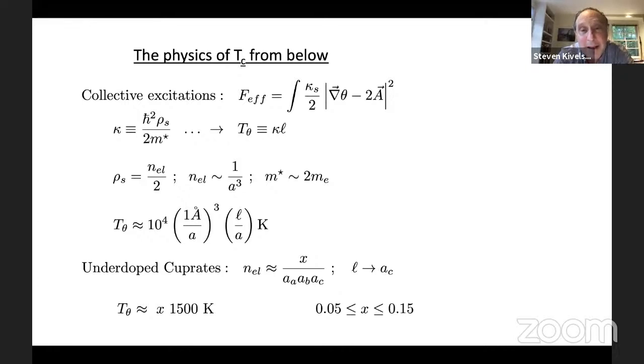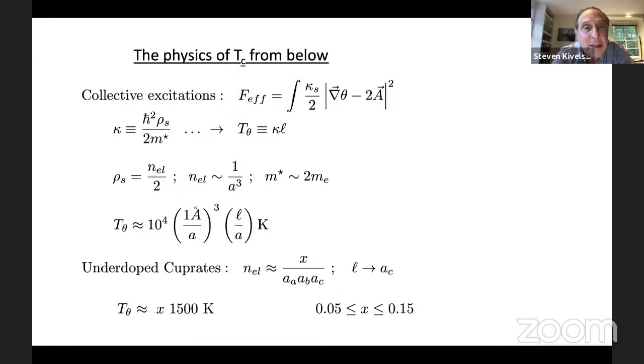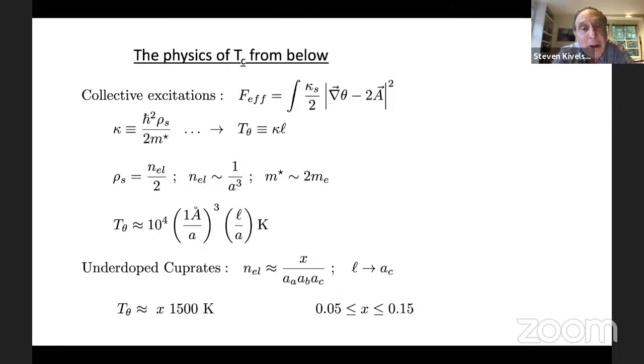L was pulled out by dimensional analysis to get a value of T-theta. In different circumstances, L will take on different values. For a bulk three-dimensional superconductor, L is the shortest distance scale on which the nonlinear sigma model description is valid — something on the order of the coherence length. In the cuprates, which are layered, L should be on the order of the spacing between layers, since the coherence length in the C direction is on the order of the distance between layers.